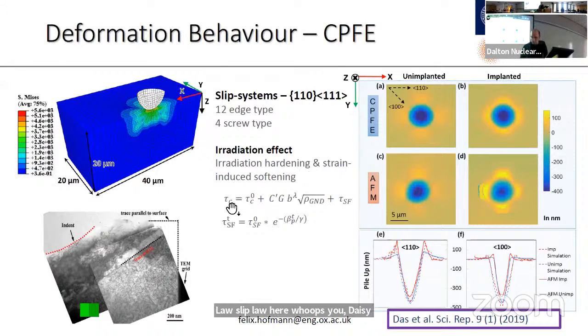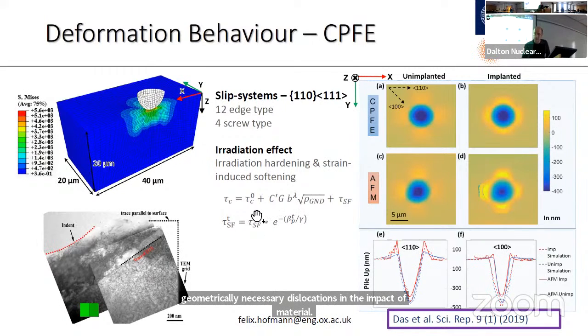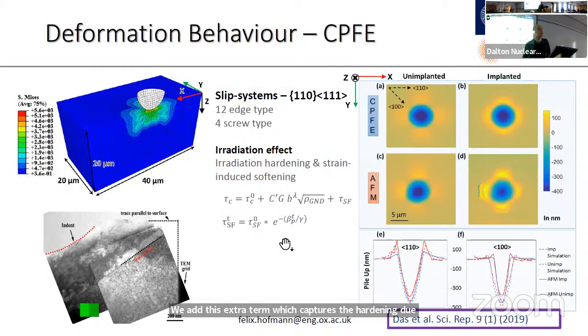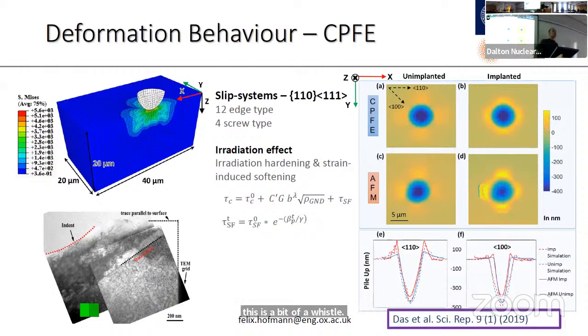So in the unimplanted material, we just say, okay, we have some critical resolved shear stress, and then a hardening contribution due to geometrically necessary dislocations. In the implanted material, we add this extra term, which captures the hardening due to helium implantation induced defects. So there's a prefactor here. This captures the hardening, and actually, sorry, I know this is a bit of a whistle-stop tour. I'm jumping over the defect, but you can write out this tau 0 SF in terms of the underlying defect population and actually find a number for that parameter based on the defects that are in the material.